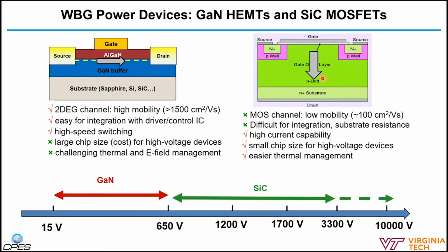That's why the gallium nitride HEMT is now commercialized at a relatively low voltage range from 15 volts to 650 volts, while silicon carbide is from 600 volts to 3,300 volts, and a pre-commercial device is up to 10 kV. Yeah, so I'm going to introduce very soon some of our recent efforts to also push GaN towards this medium voltage and high voltage range to compete with silicon carbide.